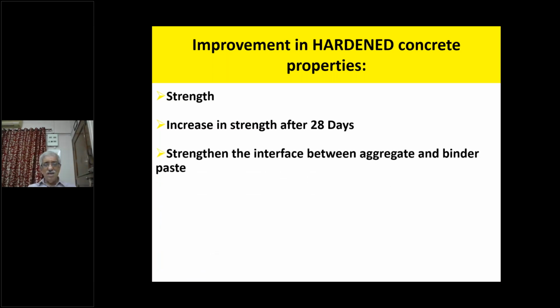Strengthening of the interface between the aggregates and the binder. You must have observed that when you crush a cube, the failure of the cube takes place, one, as a result of the aggregate itself getting crushed, or as a result of the paste getting stressed and cracked. Most of the failures of the cubes are at the interface.